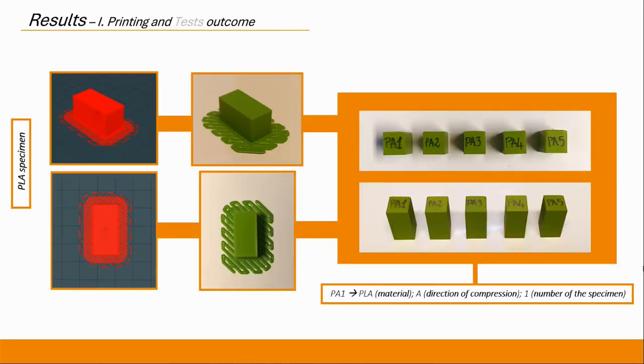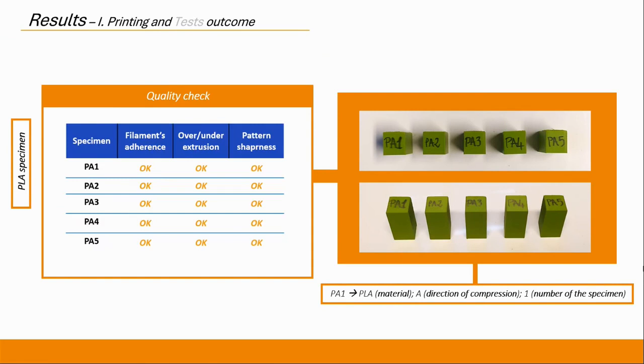Here are shown the printing stages from the design to the printing. The 5 specimens undergo the quality test. All the specimens have a good filament adherence, there aren't visible problems with extrusion rate, and the printing pattern is good. The slicing software allows us to set the infill density to 100%, but it does not guarantee that all the layers printed have this standard.